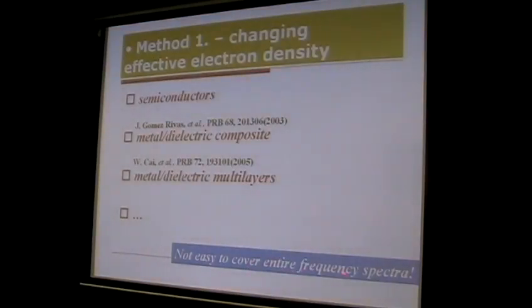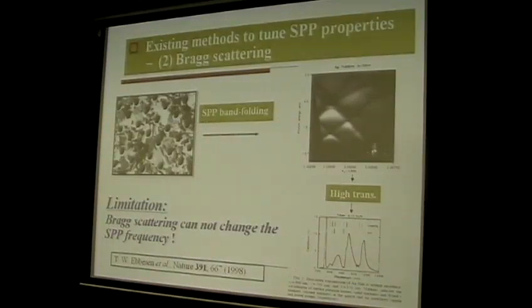However, it is not easy to cover the entire frequency spectrum. The tunability is very limited. It can only cover a small range of frequency. And also you can use a Bragg scattering mechanism to change the surface plasmon band structures. And in this famous paper, which I will go back to again, you will find that by using Bragg scattering, you can fold back the surface plasmon band into the first Brillouin zone. However, the limitation is that Bragg scattering can only fold the band. It cannot change the plasmon resonance frequency fundamentally.